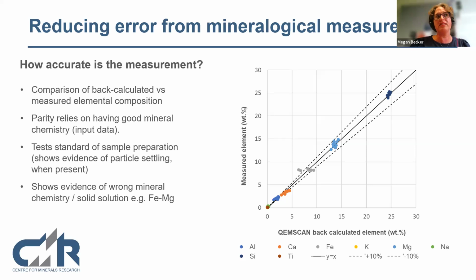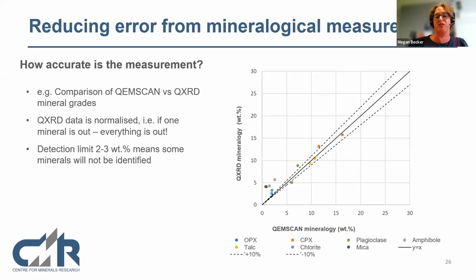But it doesn't tell me that I've got the right minerals, because I can have more than one mineral that has a similar composition. So then I will go to something like quantitative X-ray diffraction. This is another method that allows me to measure mineral grades. I might not do this on every single size sample, but I will do this again. So the QEM scan gives me a mineral grade, the XRD gives me a mineral grade, and I plot this on a line. And again, I want it to sit within the 10% bounds.